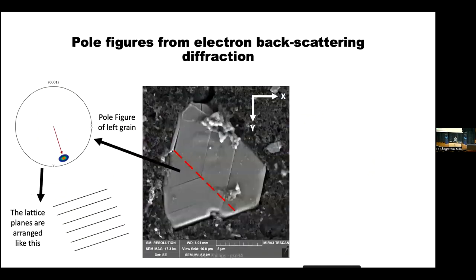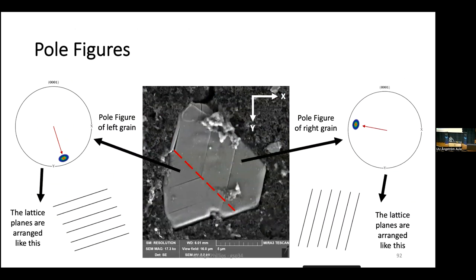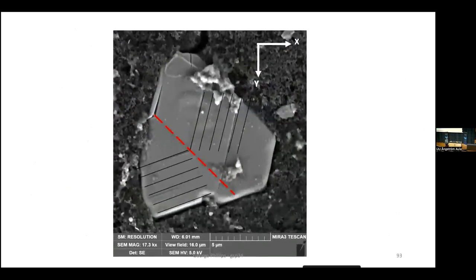To analyze what's going on, these are some electron backscattering diffraction images. You can see this particle that was looking nice before it started has really cracked. But what's more interesting is if you look at the pole images and the pole figures, you can unpick the planes in this material. You can see this is not a single crystal. It's got a grain boundary between the layers in this direction and layers in this direction. And that grain boundary is actually pinning the whole thing together. So cracking is not happening at the grain boundary. In fact, it's forcing the cracking of the layers because of that stress. This is what we're now looking at in a broader context, looking at different particles and trying to understand how the non-single crystals, or the defects within single crystals, impact degradation.